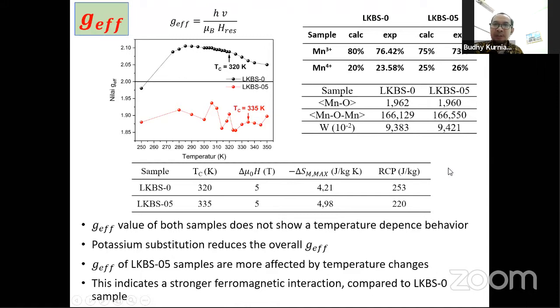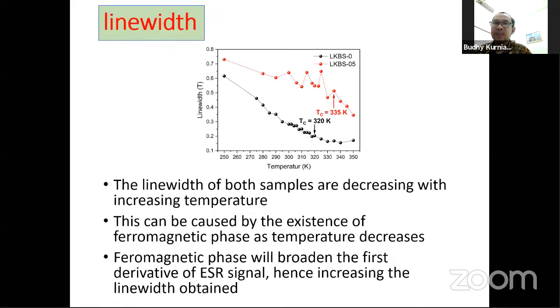What we can get from this is a stronger ferromagnetic interaction compared to LKBS 5 and LKBS 0, which can be deduced from the G value in this curve. We see that 2.00 is the free electron G value. And from the line width, we can have the summary that the ferromagnetic phase will broaden the first derivative of the ESR signal, hence increasing the line width obtained.